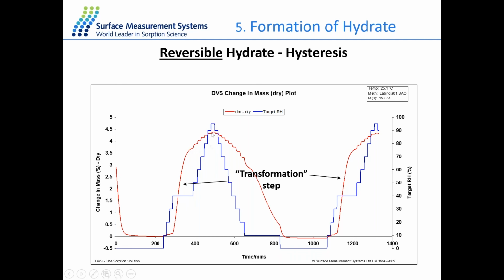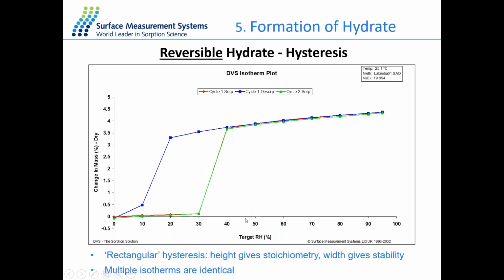And during the desorption step, the sample is losing the water and going back to the 0 point. And in the second cycle, it's at the same level as the first cycle sorption. So this is a kind of reversible hydrate formation for the sample. And when you plot the isotherm, you get this typical isotherm for hydrate formation, where at a single step you have an uptake of the water.